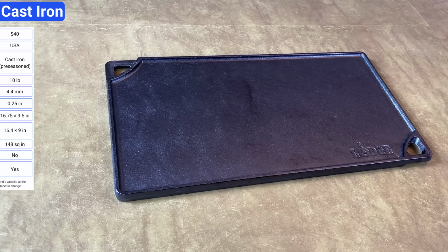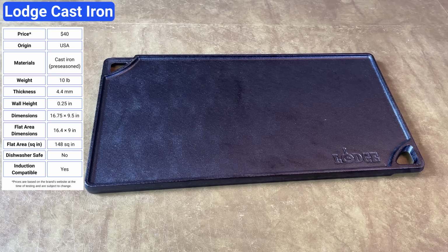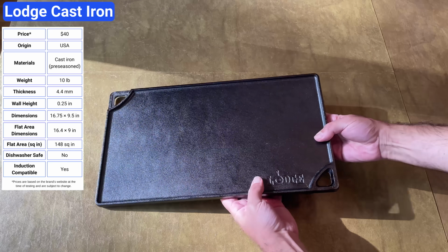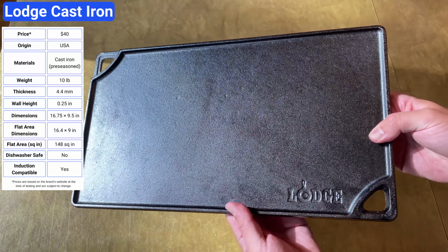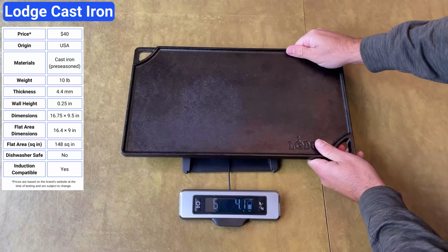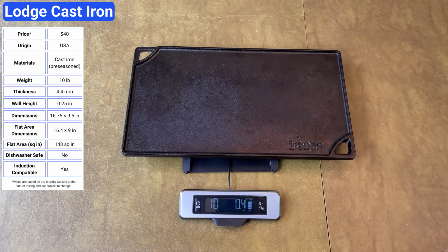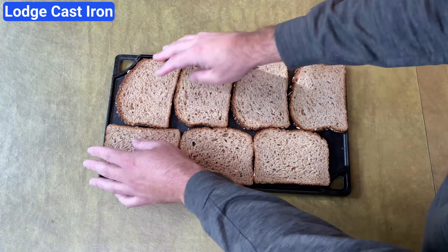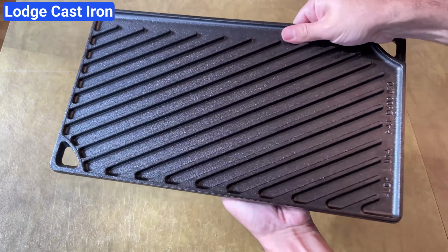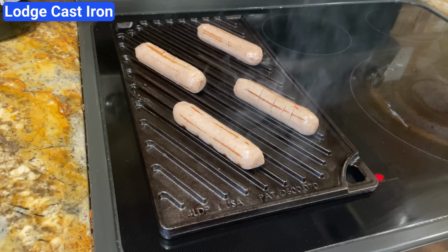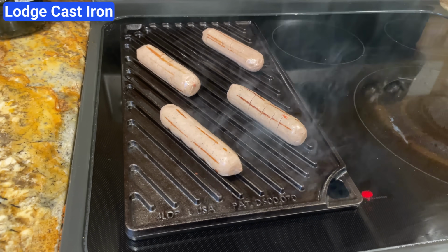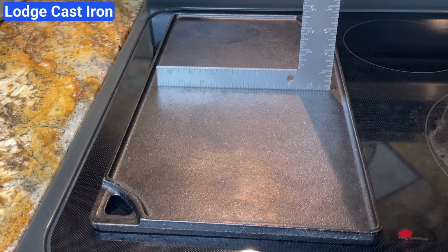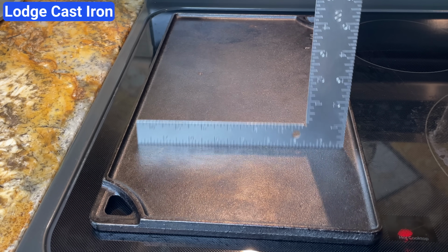The Lodge cast iron griddle is made in the USA, and the surface comes pre-seasoned. It's reversible with a flat griddle on one side and a grill on the other. It's the thickest and heaviest griddle I tested, but the cooking surface is relatively small. The biggest advantages are durability and heat retention. Unlike the Nordic Ware griddle, there's no coating that can wear down. And because it's so thick, it stayed completely flat during my warping test.